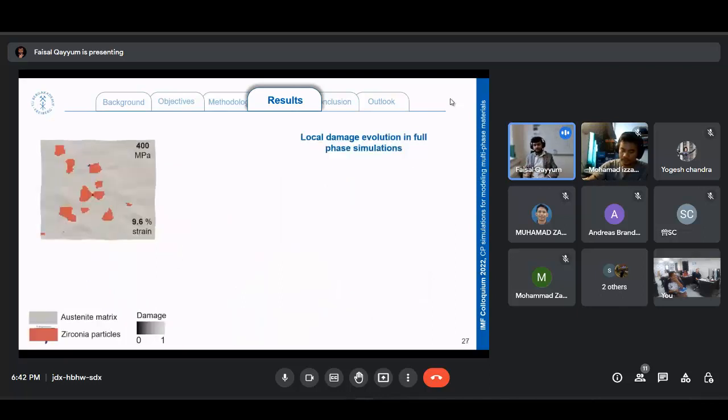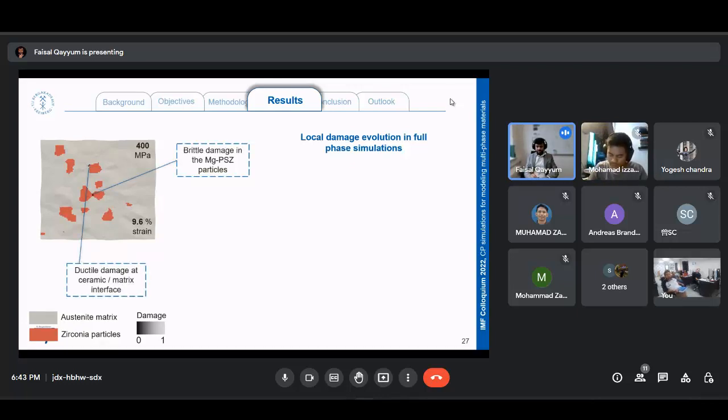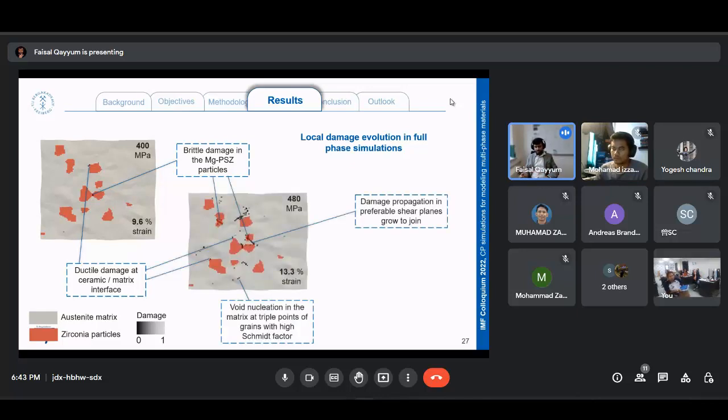Now, in this case, we were interested in looking at the damage initiation and propagation behavior. We see here that damage initiated along the weak links between the zirconia particles and also on the interface of the zirconia particles and austenite matrix. At 9.6% of the strain, we see this image. Then at higher strains, for example at 13.3%, we see that the stress in the material is still increasing. The interface decohesion continues to grow, there are more zirconia particles cracking, and void nucleation at the triple points in the material also